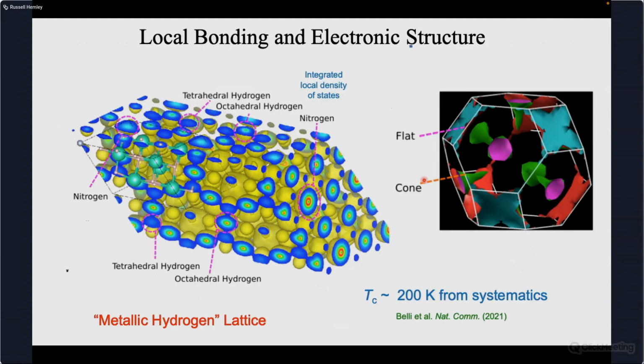We now turn to real space and look at this structure here. And here we're plotting the integrated local density of states. What we find for this particular packing sequence or stacking sequence of layers is basically an embedded net of metallic hydrogen, where you have the hydrogens basically touching each other in atomic hydrogen. And this is characteristic of all of the superconducting hydride systems. And if you use various systematics to predict or estimate the TC based on this model, and this goes back to some work that was done by Belli et al. several years ago using those techniques, you can estimate TCs that are quite high. Also, it has a very interesting Brillouin zone, which shows the flat bands and cones. So it's a very interesting topological material as well.